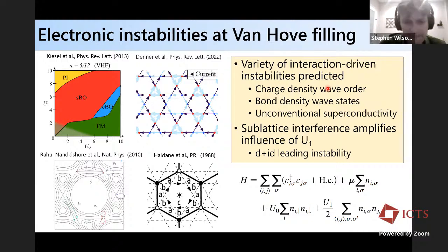And one of the oddities is that in the weak coupling limit, if you're at this p-type Van Hove singularity, then the on-site Coulomb interaction is severely diminished or vanishes, and it really promotes the influence of extended, nearest neighbor Coulomb interaction or further exchange terms. And so depending on the details, there are interesting phases, for instance, a so-called orbital flux phase or an imaginary charge density wave phase, which is a form of orbital antiferromagnetism, which maps to some of the original states predicted by Haldane in honeycomb lattice systems, as well as instabilities of unconventional superconductivity, for instance, d+id superconductivity, also originally predicted in honeycomb lattice systems in this paper by Nandkishore and Chubukov.